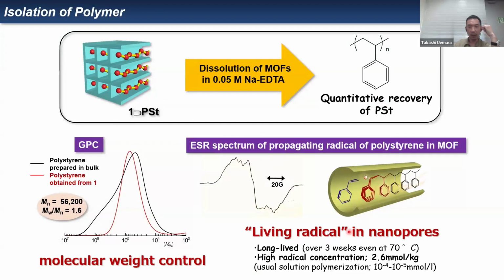So now we could obtain the polymer composite. But how can we isolate this polymer composite? How can we isolate the polymer from this composite? Here, it's very simple because this is a coordination compound. So here we just digest the framework by dissolution of the framework in a chelating solution to give the polymer quantitatively.